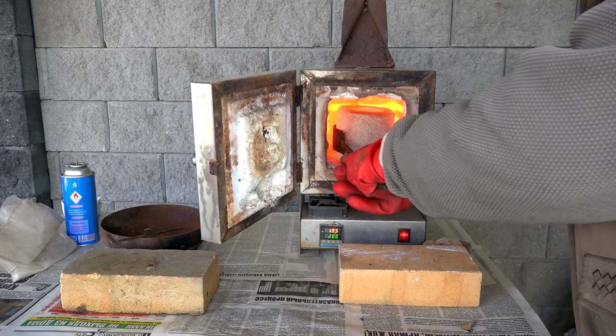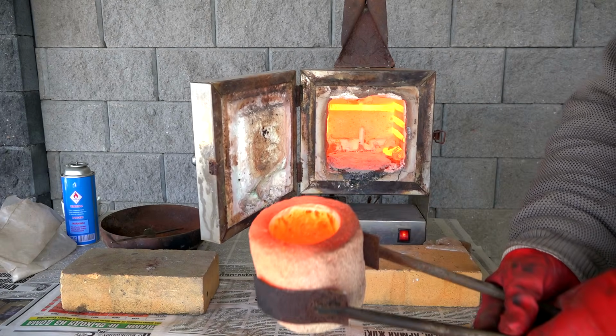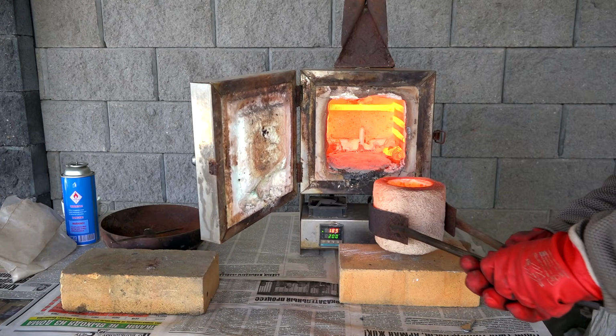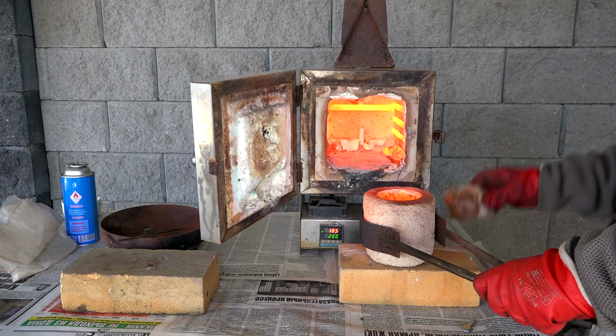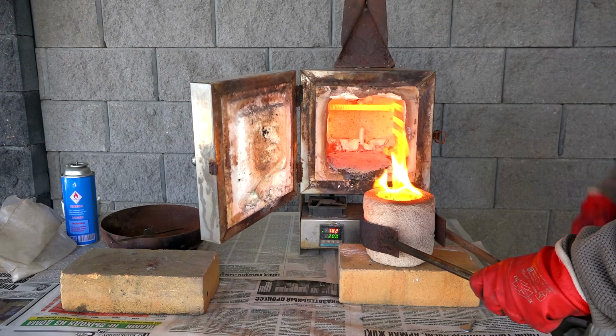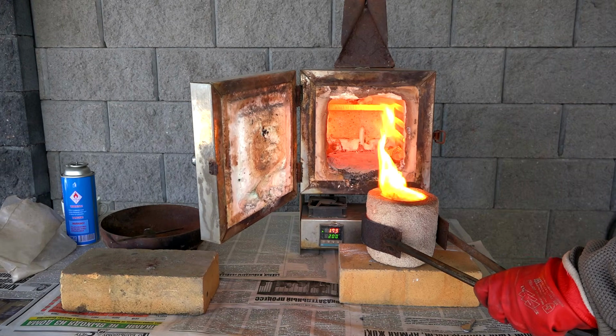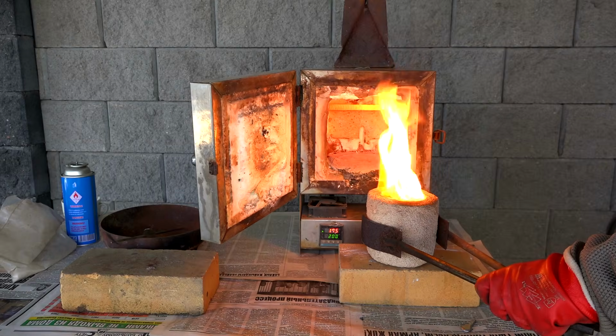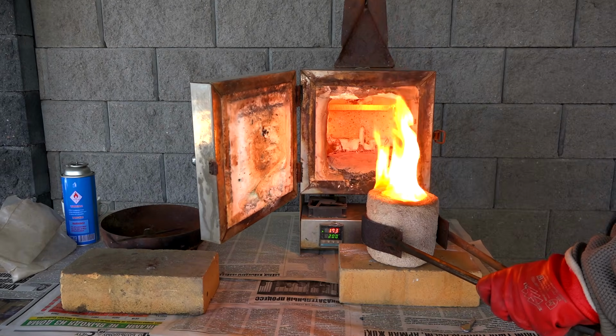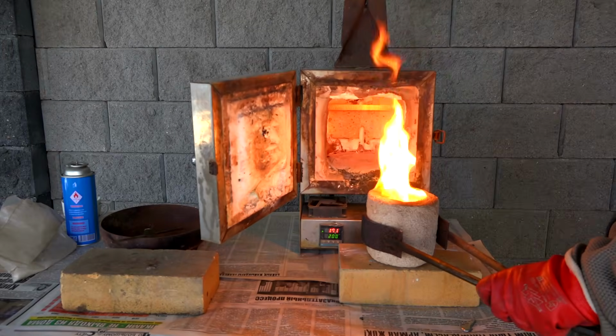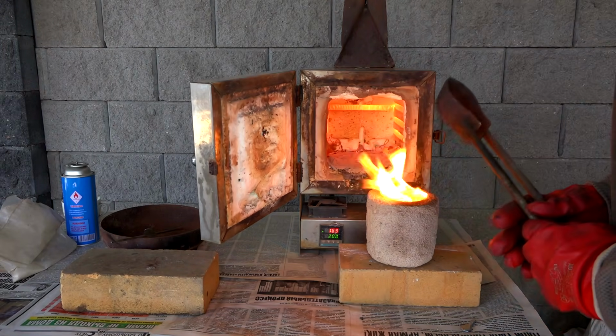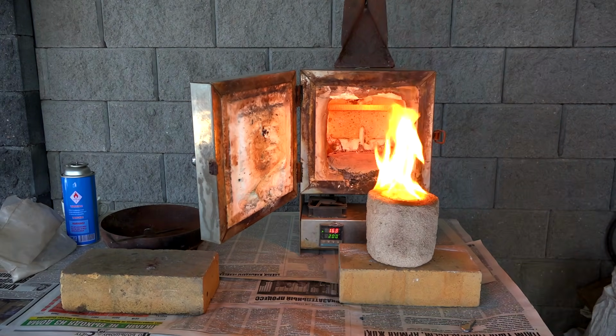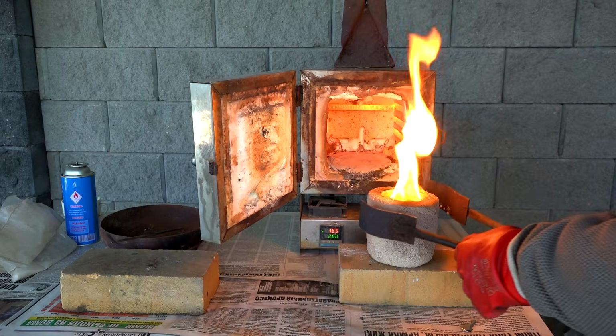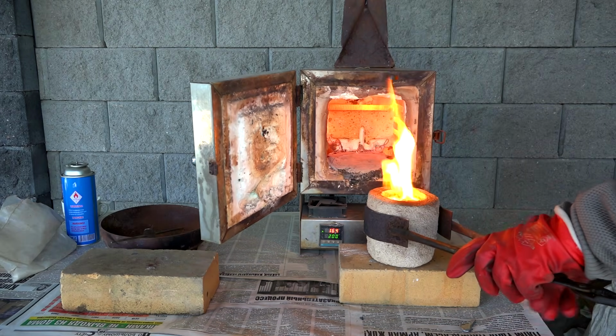The first portion warmed up and melted after 1 hour. 200 degrees are displayed on the muffle furnace controller, but in fact it is already 800 degrees. This is because there is no thermocouple in the furnace. I just twisted the wire in place of the thermocouple, and this causes incorrect readings that only I understand. The moment came to add the rest of the concentrate. Everything melted perfectly. The crucible did not burst.